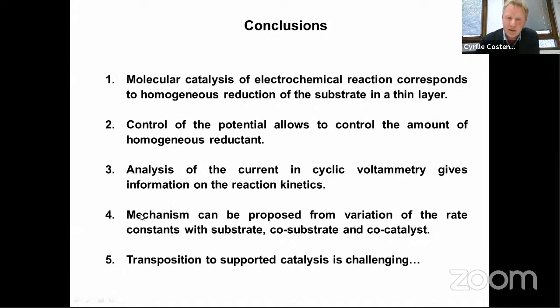And then from this kinetic information, you can propose a mechanism, and you can get more insight into the mechanism by changing either the substrate, the co-substrate, or the co-catalyst. And with all this information, you can design better molecular catalysts. Then the next step is transposition to supported catalysis. But as I tried to show you at the end of this talk, it is kind of challenging. And I think this is the next direction the field should move on